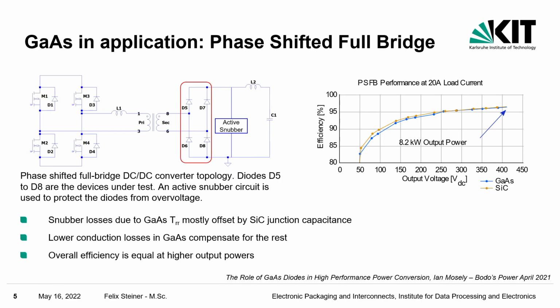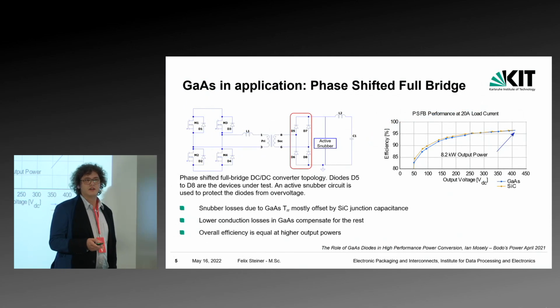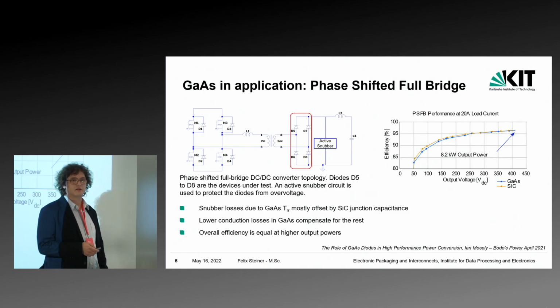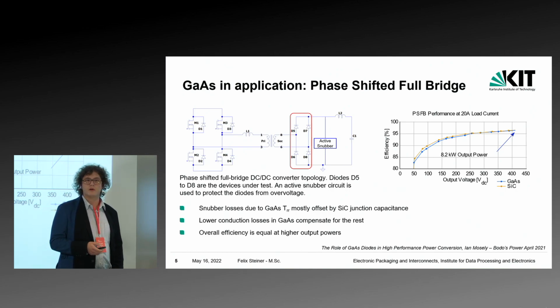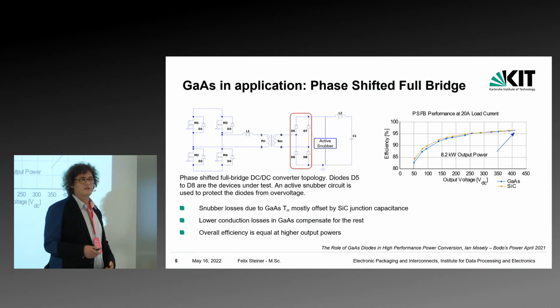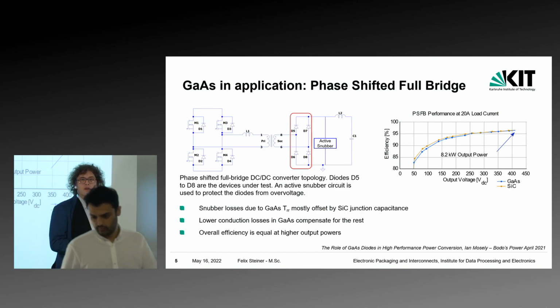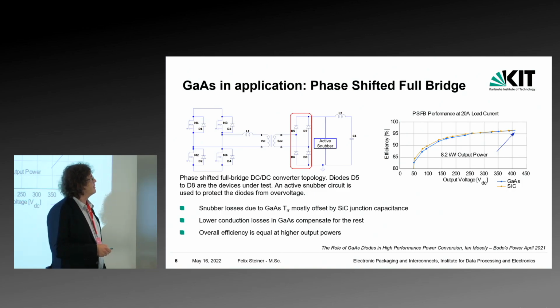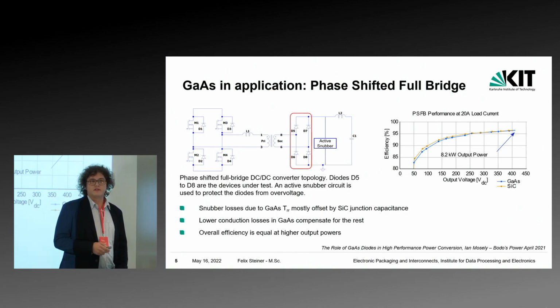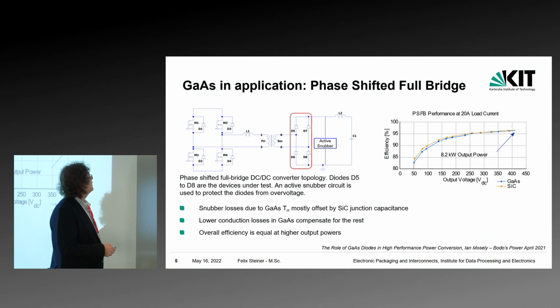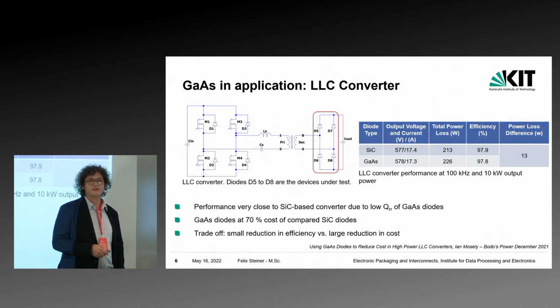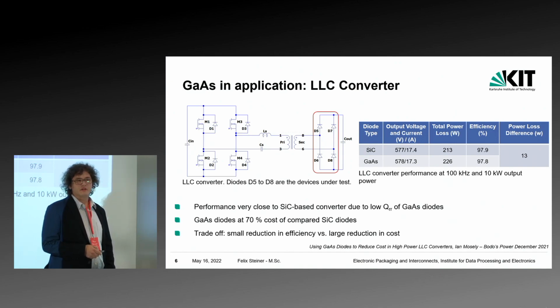And you can see that you get almost the same switching losses between gallium arsenide and silicon carbide, despite the nonexistent reverse recovery in silicon carbide, which you still have with gallium arsenide, but the junction capacitance is just so low with the gallium arsenide diodes that it balances out a little. And the rest is basically compensated by the lower conduction losses. So in the end, you get more or less exactly the same performance here with 8.2 kilowatt output power at the same efficiency. And in a second evaluation with an LLC converter, we can see a very similar result.